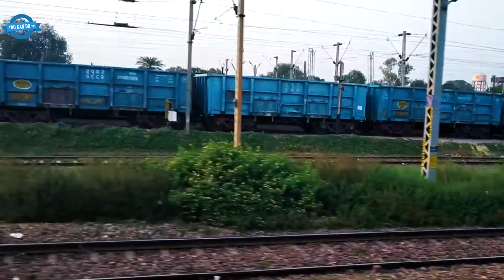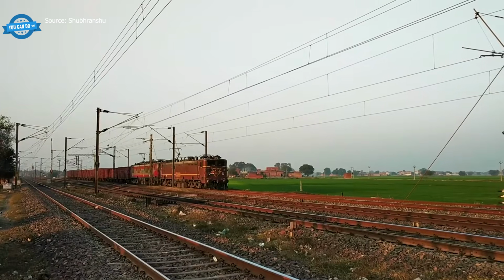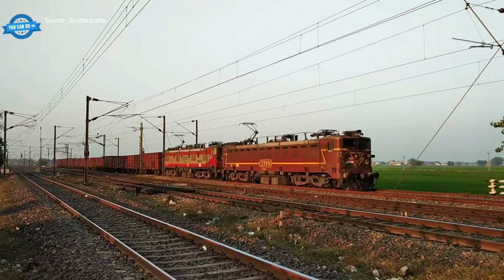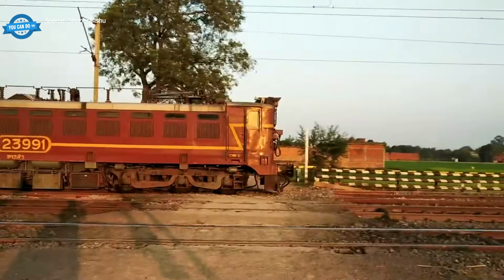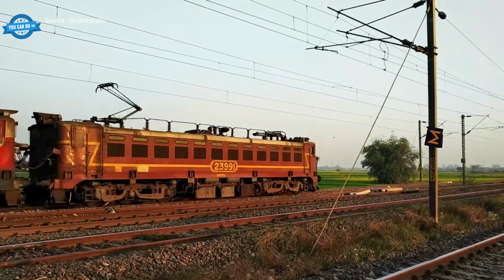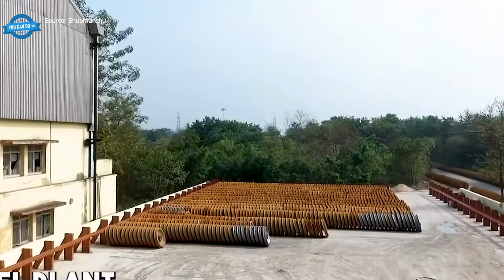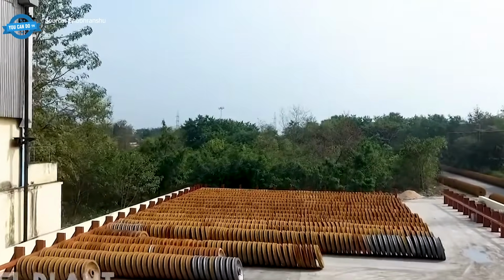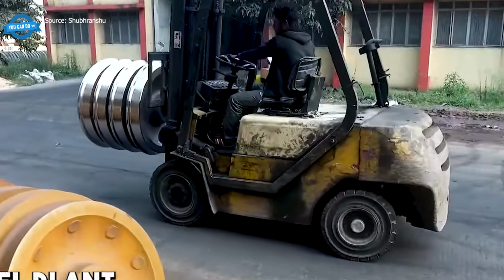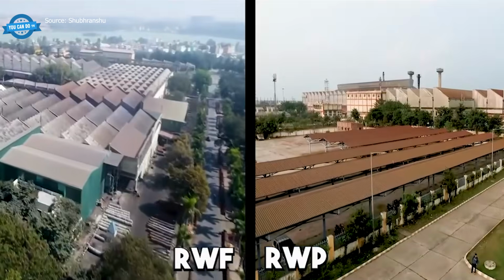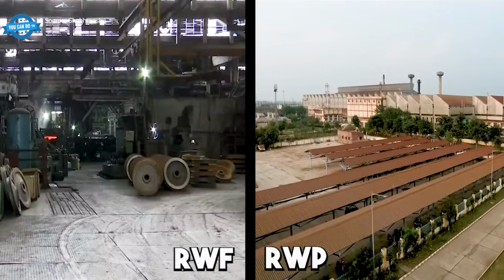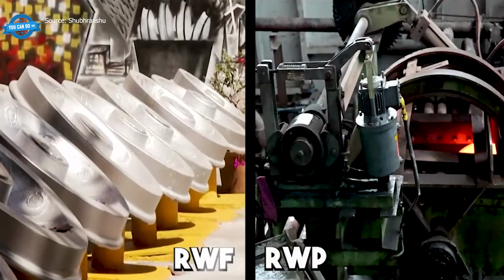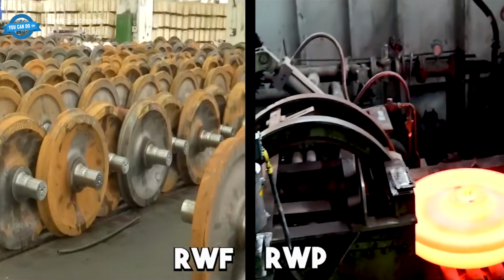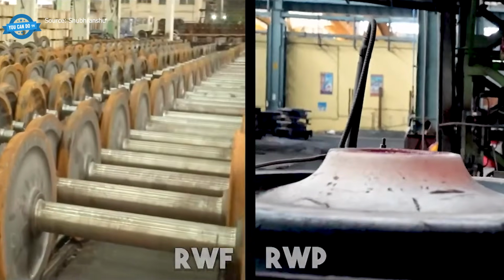Now, put a train on top of a wheel and multiply by 200 cars. A railroad wheel carries 15 to 20 tons of load, at speed, over rail joints, for years, with the only rest coming when a bearing seizes and the maintenance crew swears at somebody. The wheel plant at Bela uses bottom pressure pouring of molten metal into graphite molds, one wheel every 2 to 3 minutes at peak. That is the cast route. The forged route, which we will come back to, is used where the load is even nastier.